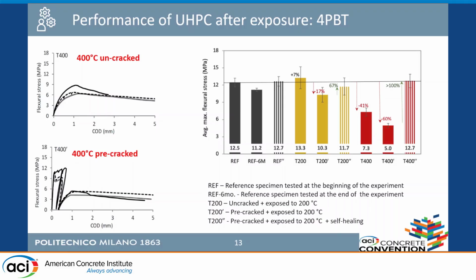How can this happen? Because we have the closure of the cracks. We have also the reduction of the dimension of the pores, and we also have a recovery of the bond of the fibers and the matrix. I didn't stress this in the tables of the mix design, but in the mix there is also a penetron admixture, a crystalline admixture that fosters the closure of the pores, because it is a reactive material, and so it reduces the permeability, and this emphasizes the effect of self-healing.